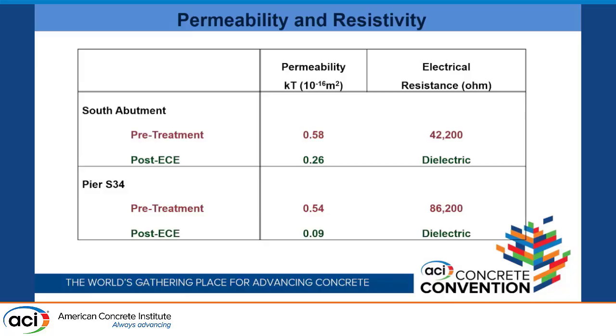And this is one of those things where you really have to look at the details of what was done in the different cases to figure it out. And this whole issue comes down to the electrolyte that was being used to do the work. So in the laboratory work that was being done, and the SHRP program, and I think you used the same as what was being done there, they were using sodium-based electrolyte. Sodium borate was the common one that was used at that time. And in the field, we were never doing that. We were using basically lime water, so calcium hydroxide solution.